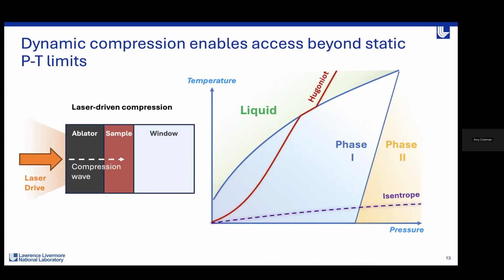So, in a laser-driven experiment, we're looking at a setup as I'm showing on the left-hand side here. We have a laser which is incident on a target package, which is typically made up of multiple layers, including an ablator, a sample, and then some sort of window at the back. The ablator is typically a low Z material, and this is the section of the target that interacts directly with the laser. What happens is our laser is incident, and it creates this big plume of plasma on the outside of the target. In reaction to this plasma plume, a compression wave is launched into our target package, and this is done via something called the rocket blow-off model.